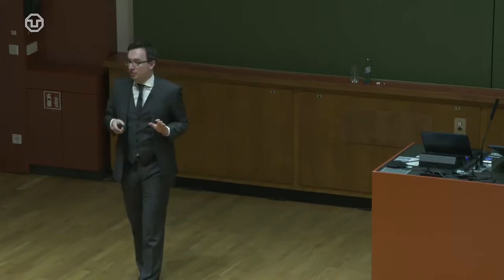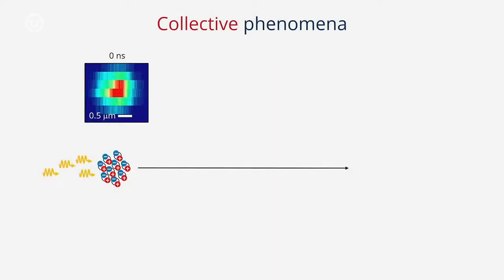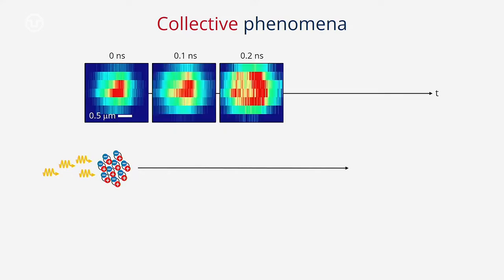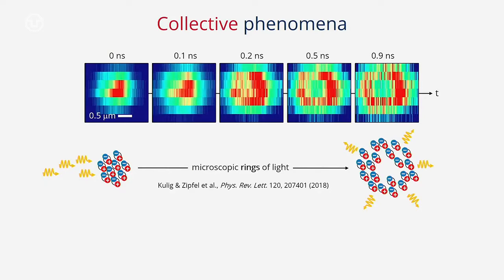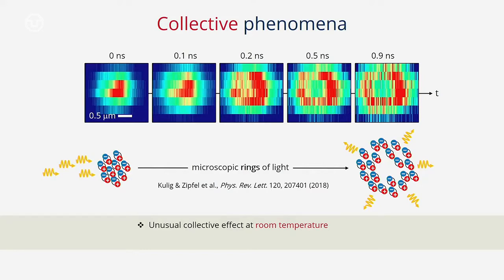In addition, there are all sorts of very interesting collective phenomena. I will not go into too much detail, just show you one. When you inject a lot of these particles, a very interesting effect happens. Instead of just diffusing very trivially, they form rings. It's an indication of interactions. It's an indication of memory effects, if one thinks about it in a little more detail. But also, it's a phenomenon that happens at room temperature, and this is very unusual. People saw such an effect before in gallium arsenide 10 years ago, but it's all at cold temperatures. Here, we see such collective phenomena, such ring formation, at ambient conditions.